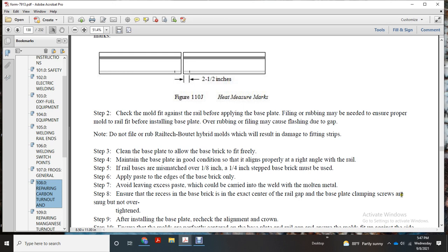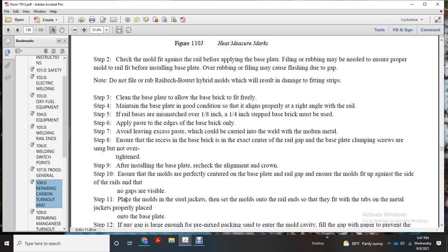The base plate clamp and screw should be snug but not overtightened. After installation of the base plate, recheck the alignment of the crown. Ensure the molds are perfectly centered on the base plate and rail gap. Ensure the molds fit up against the sides of the rails and that no gaps are visible. Place the molds in the steel jacket, then set the molds onto the rail ends.